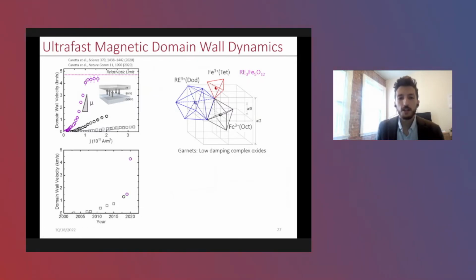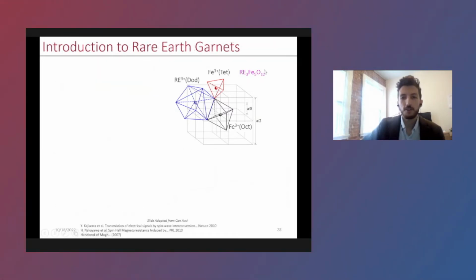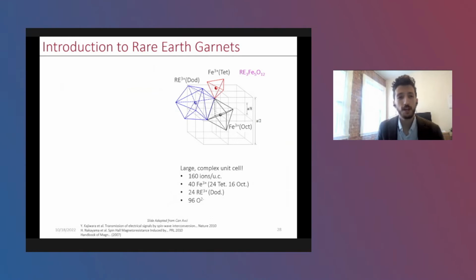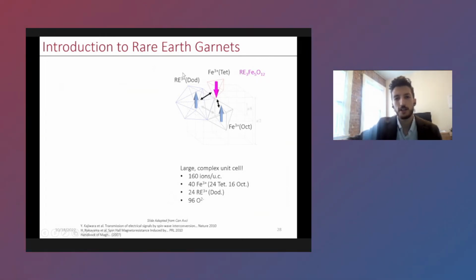And so let me first describe a little bit about these types of garnet materials, more about their structure and their magnetic structure as well. They're very complex oxides. They have very large cells with ions sitting in many different sites. But magnetically speaking, they're actually quite simple. They consist of just 3 magnetic sublattices, an iron tetrahedral sublattice, which is antiferromagnetically coupled to the rare earth dodecahedral site, if you choose to use a rare earth, and of course the other iron sublattice as well. And the interaction between the octahedral site and the dodecahedral site is quite weak, so we typically neglect this.